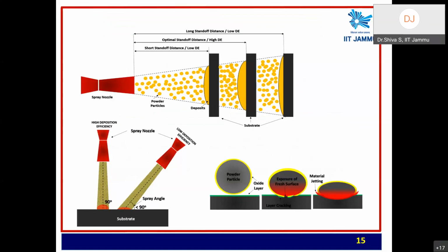Unless you are meeting that maximum speed, the impingement of powder is not going to be as easy as it is shown here. So to have that impingement done much more efficiently, you have to ensure that the standoff distance between the nozzle and the substrate is optimized. Because if you are moving the substrate plate randomly away from the nozzle, you can see the deposition efficiency for a short standoff distance will be low.